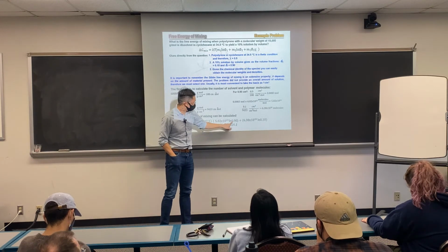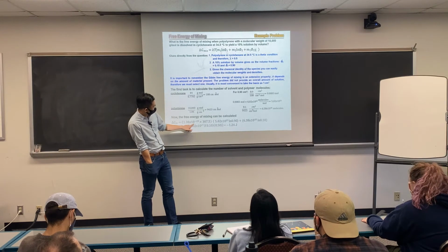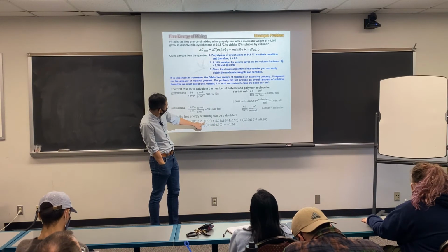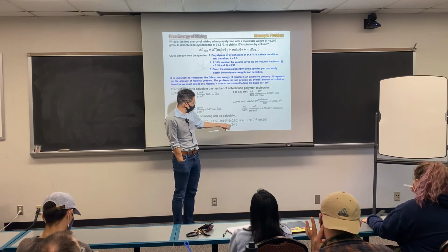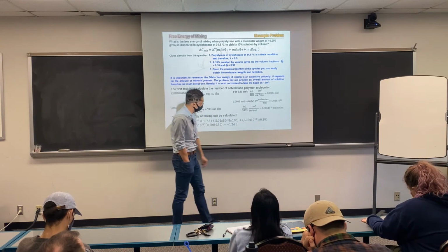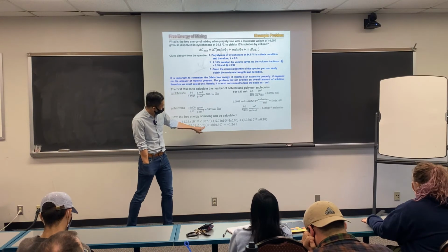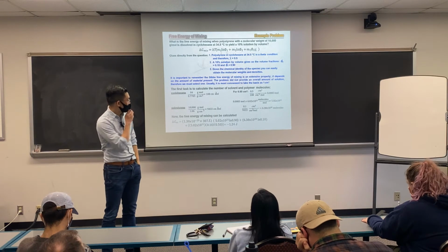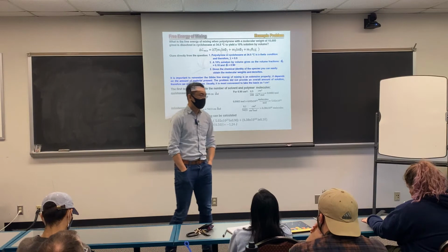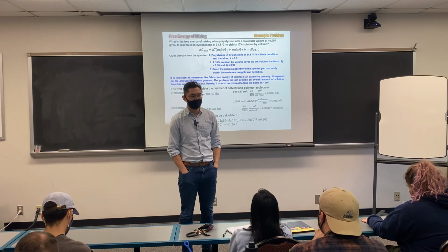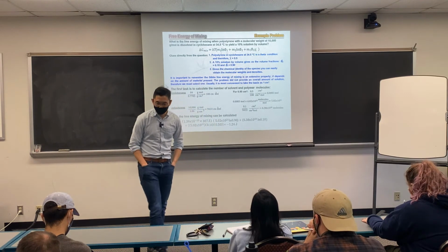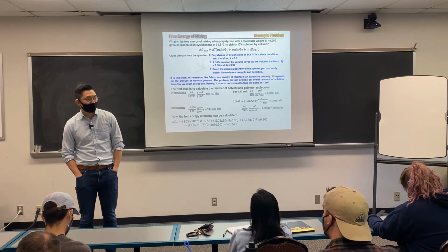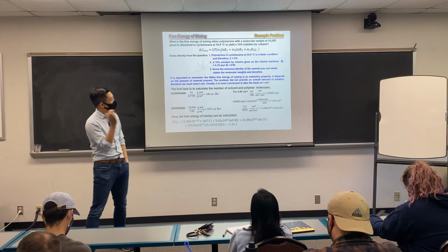So using that, you can calculate the delta G of mixing. This is the gas constant, multiplied by T, the temperature. The number of solvent molecules times the log of its volume fraction, plus the number of polymer molecules times the log of its volume fraction, plus the number of solvent molecules times the volume fraction of polymer times the chi parameter. That will give you the delta G for the system. Okay? So the delta G is basically minus 1.24, and we know the polystyrene will be happily dissolved in cyclohexane. So you can apply similar questions to other systems, other solvents. Pretty useful, I would say, in practical use of this Flory-Huggins theory.